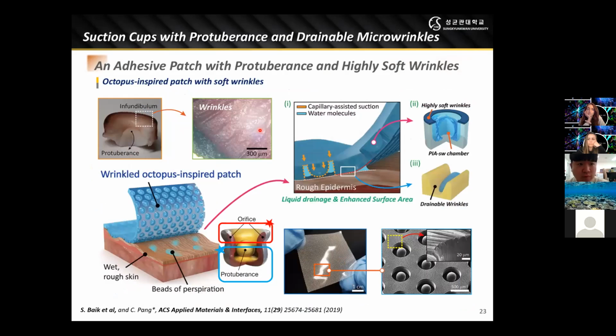Next, we found that the micro wrinkles on the suction cup surfaces would assist to enhance the wet adhesion and water molecule management. So we added soft wrinkles on the previously developed suction cup chambers with pores for high drainability and robust attachment against dry and wet human surfaces.